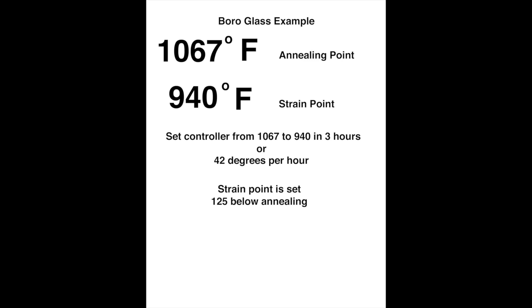The thing about borosilicate is once you get down to the strain point, and the same with any glass, once you're below the strain point, you can't add or take away any strain. So you can cool down the glass as fast as possible as long as you don't thermoshock it. So especially with soft glass, you want to go through the second step. And you want to get it to slow down enough that you don't have thermoshock. But in most cases, with borosilicate, you can just shut it off once you're through the strain point.